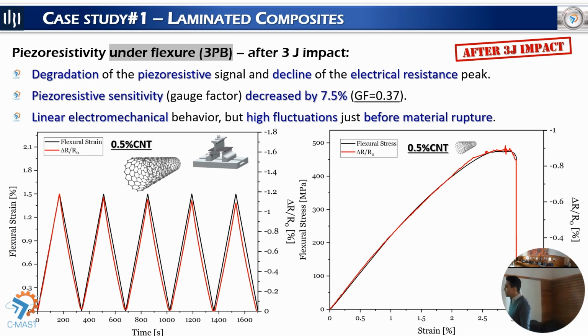We can see here some deviations of the electrical signal in the red line against the black one, which corresponds again to the mechanical signal. We can see that we have some deviations during the experiment. This means that the sample that has been subjected to impact tests before presents some damage, and the correlation between the mechanical and the electrical signal is not the same as we had at the beginning. So this is working as a sensor.